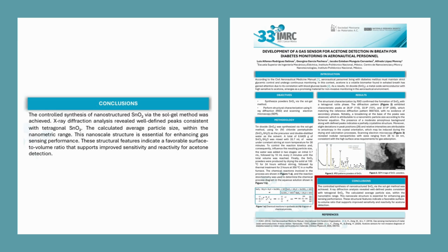In conclusion, the Sol-Gel method allows us to obtain nanostructured tin dioxide with tetragonal rutile phase and nanometric particle size. These structural characteristics generate a high surface to volume ratio that enhances sensitivity and reactivity, making the material a promising candidate for acetone detection. This represents an important step toward the development of a non-invasive gas sensor for diabetes monitoring, particularly useful in aeronautical applications where continuous health monitoring is essential.